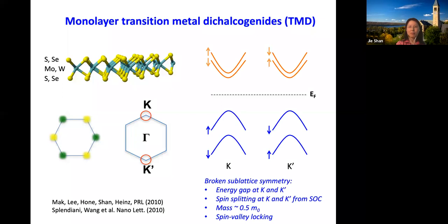About a decade ago, we and our collaborators discovered that in the monolayer limit, this class of material becomes a direct bandgap semiconductor. In the bulk form, they are indirect bandgap semiconductors, by the way. The gap occurs at the K and K prime points. What I'm showing here is the simplified electronic band structure of this material near the band edge. The gap here is about a couple of eV.